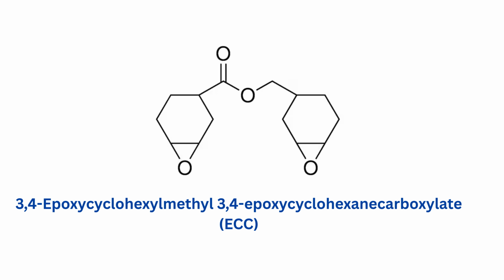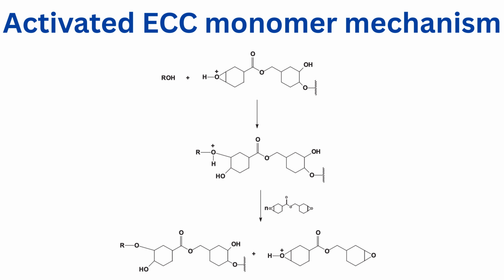Conversion of ECC alone in standard conditions is usually in the range of 40 to 60%. Therefore, both brittleness and a low conversion degree often make ECC unsuitable to be used alone for industrial applications. In order to find the right balance between high curing speed, high conversion level, and limited brittleness, it is required to blend ECC with other ingredients.